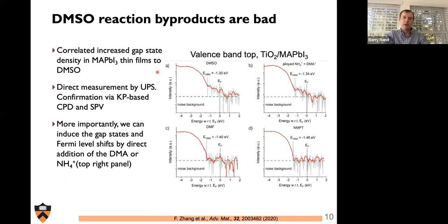And what we found was, looking now at some UPS data from Antoine Kahn. So what this is showing is the valence band, the start of those filled states in the methylammonium lead iodide on titania system. And what you're looking at here, let's look at the DMF, pure methylammonium lead iodide film, is the forbidden gap here, here's the Fermi level, and then the forbidden gap, and then the start of filled states. And you can see that those filled states become more and more dense as you go further into the valence band to the tune of a couple of eV.